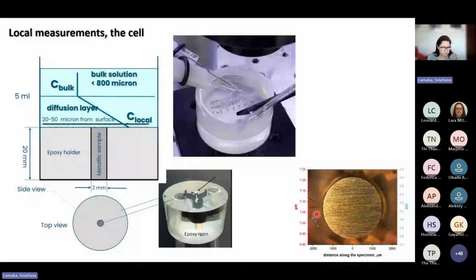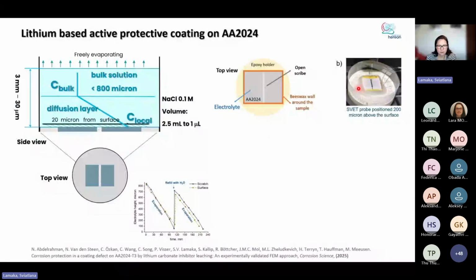So then we also made a special cell for this measurement. This is the SVET setup, but also for some pH and oxygen measurements, we simply restricted the volume of electrolyte by this glue, this hot glue. And so then the volume of electrolyte was very small to increase concentration of active inhibitor. And then we measured inside this scribe.